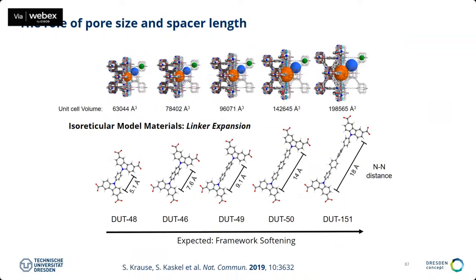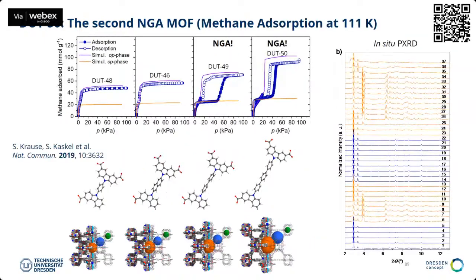So we did this by chemistry. We made all the different materials here with a small connection, a longer naphthalene connection, biphenyl, triphenyl, tetraphenyl. This material is interpenetrated, so it's a little bit different structure. But what you can see is basically for the small column, the very thin, short column, the material is rigid. You see no hysteresis in this case, but only when you have the biphenyl and the triphenyl, then you have the typical negative gas adsorption and the hysteresis. So in this sense, you can micro-engineer, you can rationalize how you can construct these types of materials.